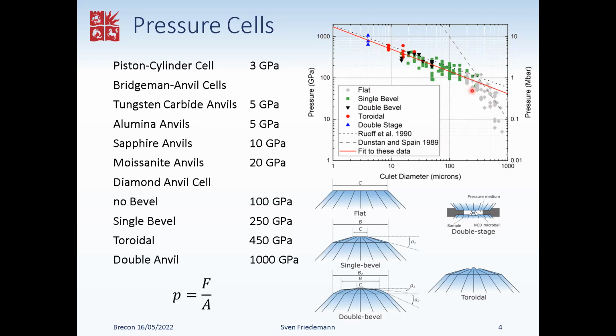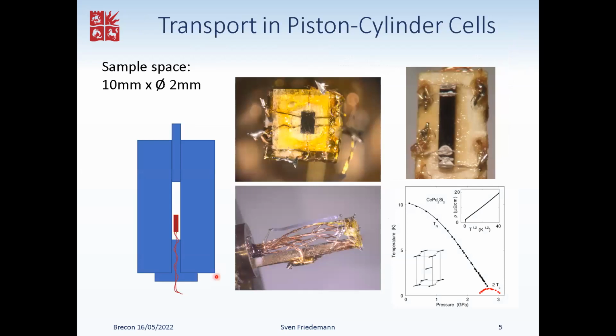Okay, so let me come back first to how pressure cell experiments are set up in piston cylinder cells, because I started with that. Electrical transport measurements are one example, which I've done quite a bit. Essentially what you do is you make a feedthrough where you've got the wires going through the closed plug. Here the principle is that you pot the wires in with some epoxy which contains sapphire powder, and because it becomes narrow, as the pressure is applied, the sapphire grit is compressed and is essentially stuck. Like if you think of an hourglass, if you had some larger grains of sand, it would gridlock in there. And that's the same principle here.